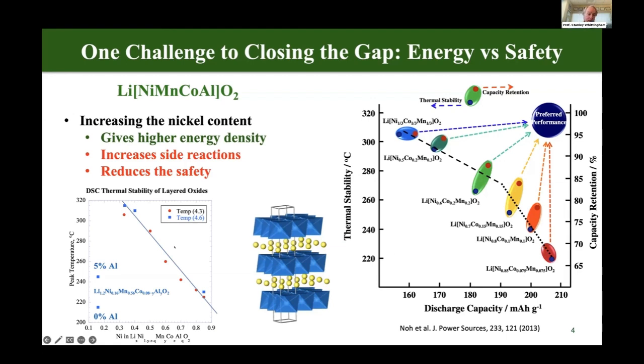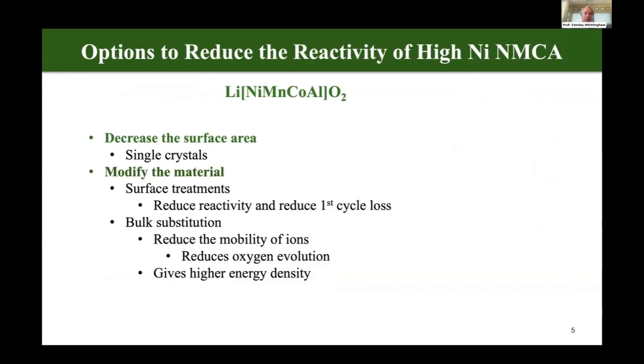And it really doesn't matter how high you charge these materials. The thermal stability is directly related to the nickel content, with a few other variations, but essentially it's the nickel content. So as you push the nickel content up, which is what we want to do to get higher energy density, we have to reduce the reactivity of these materials. So there are a number of options to do this.